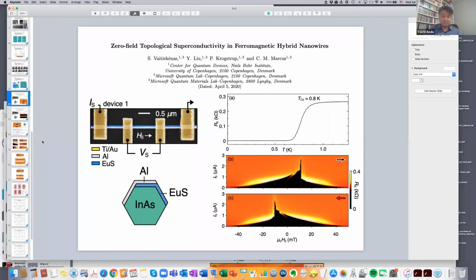So the fact that our induced gap was 4 times smaller than the bare gap, I needed to come up with something that allowed it to be a rounded transition so that it could go down that cliff. And I think that the thing that makes it rounded is spin flip scattering. And I think it's from the rough interface. There's also spin orbit. Of course, it wouldn't be a Majorana without spin orbit. And the aluminum does leak into the semiconductor to some extent. But I think that it's the roughness that gives an effective spin flip scattering that reduces the gap and makes it second order. Okay, then maybe this enhanced spin flip scattering is the reason why you don't see the splitting coherence peaks. Correct. I think that is correct.